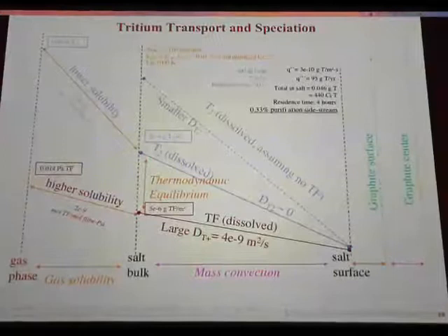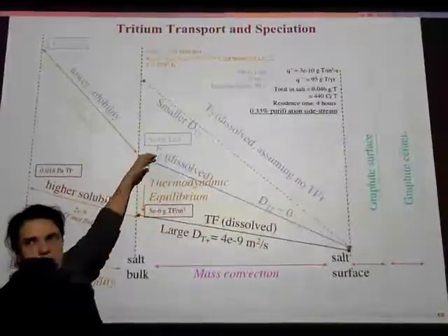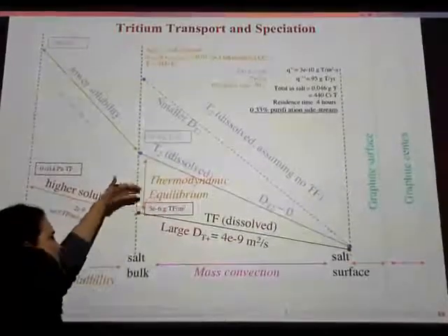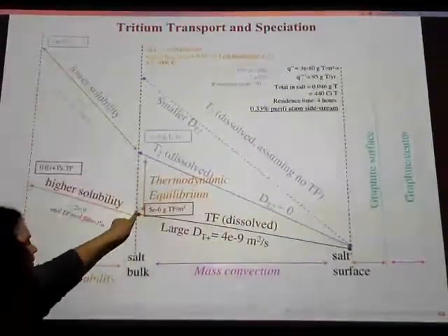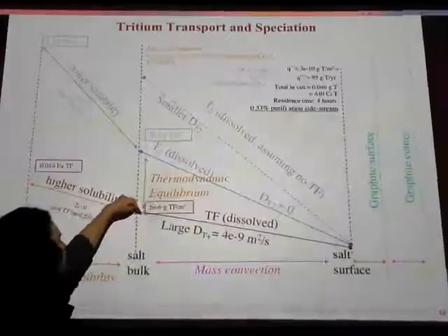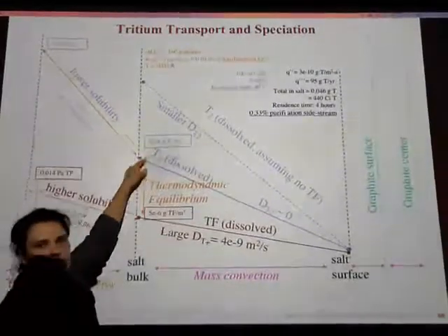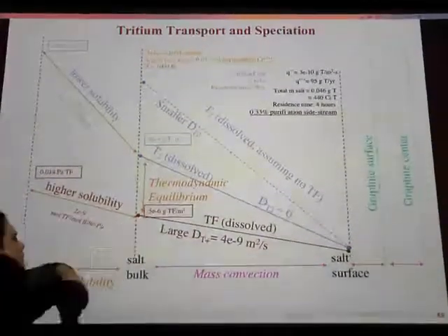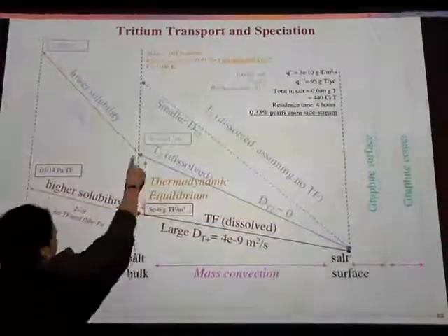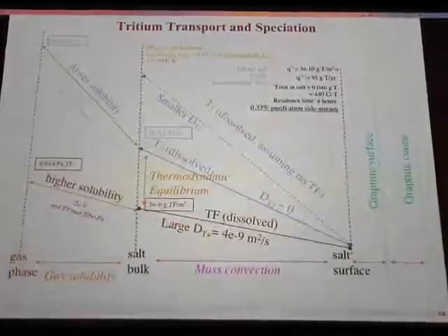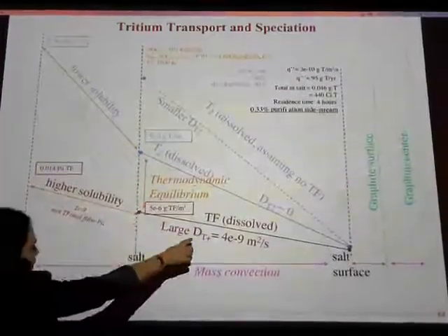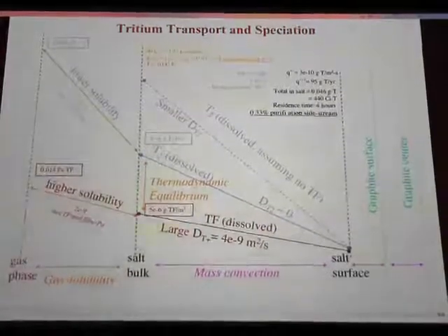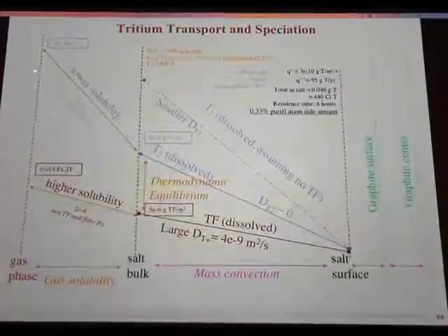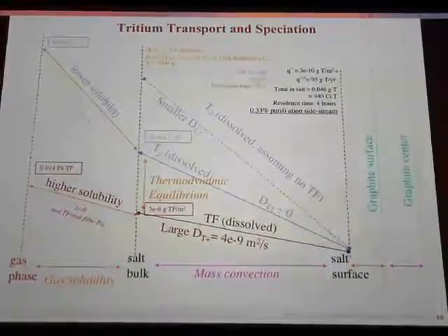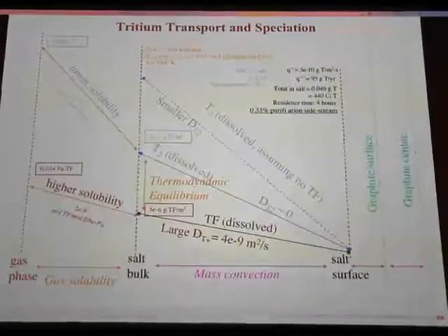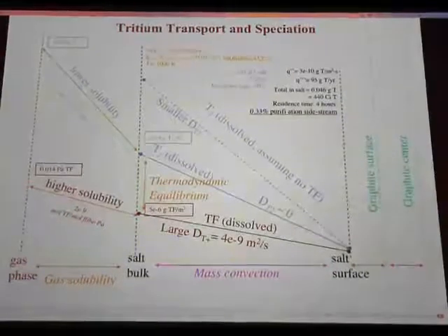So you're going to set your chemistry control system so that it's somewhere towards the 0 oxidation state. And it's going to have an effect on tritium as well. So it's going to be pushed towards here. And so if you need this T plus concentration to drive the mass flux, it means that you need this T2 concentration that's in equilibrium with this T plus concentration. So then from there, each of these species has a partial pressure above it, above the salt in the gas phase. And so we can calculate what that is. For T plus, it's 0.01 Pascal of TF. And then for T2 is kind of high. It's 180 Pascal T2. It's higher than I would have expected. I think that's going to be a pretty good driving term for leakage through the heat exchanger.